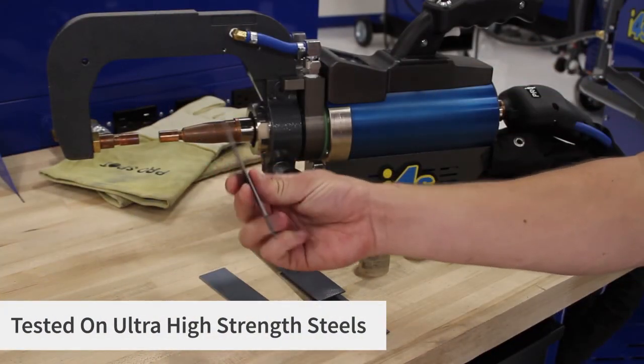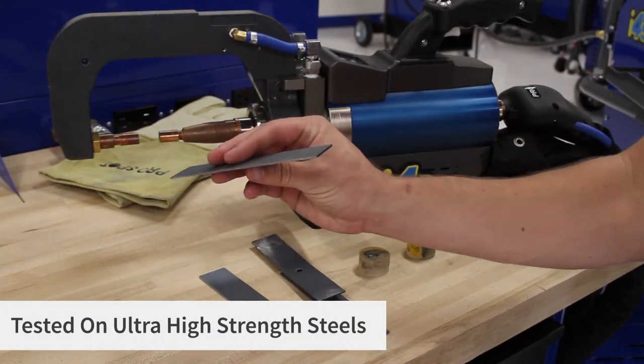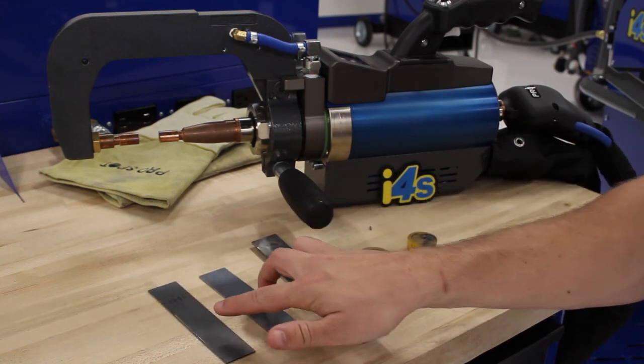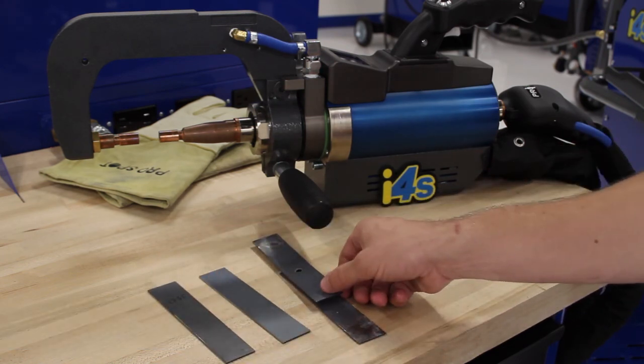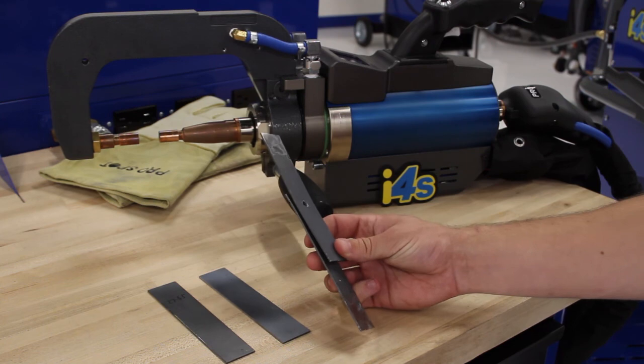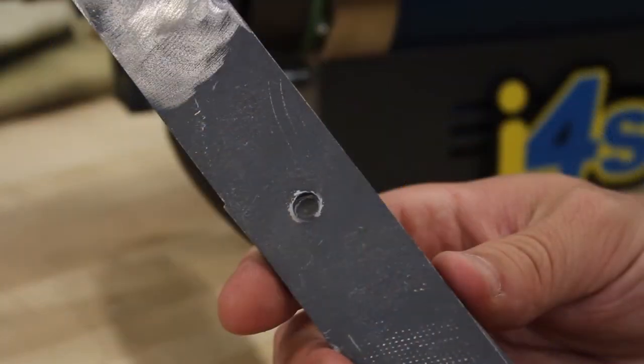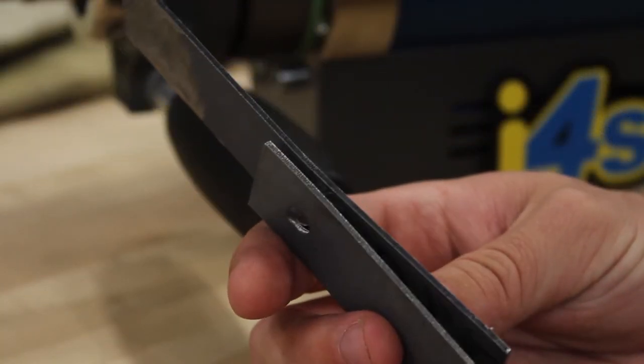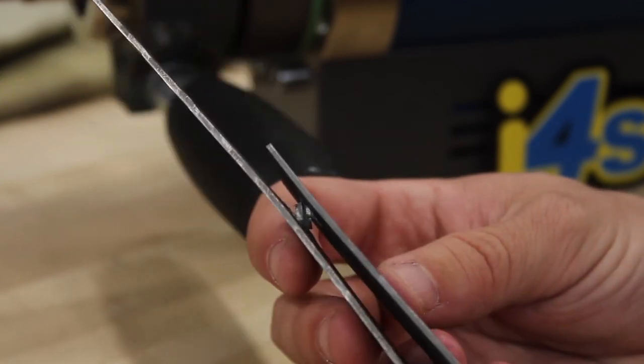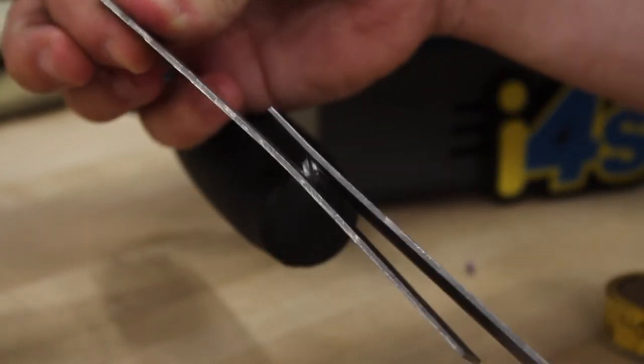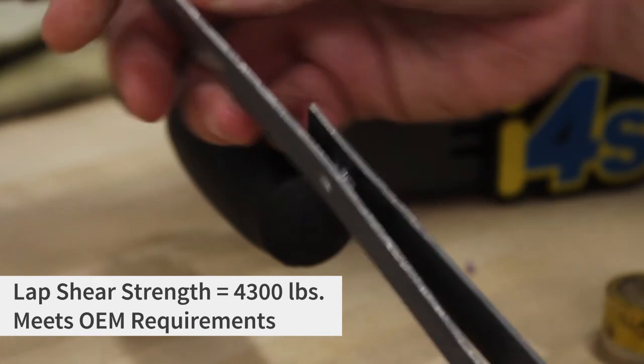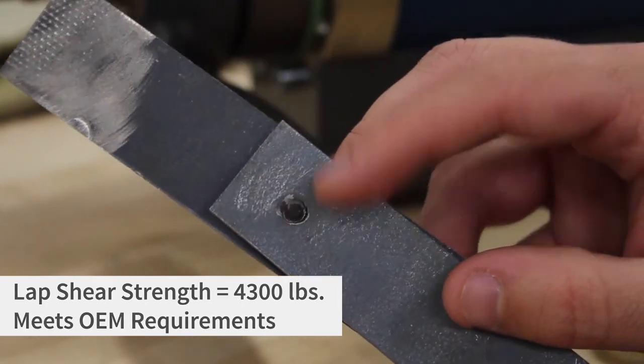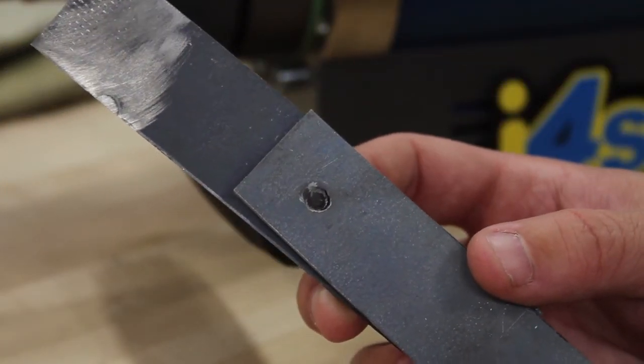So this is some of the high strength steel that we use for testing and evaluation. So first we start out with these two coupons, and then we actually spot weld them together and we find the pull strengths. So once we get a good recipe for the weld, we actually do a pull test on it. So we're actually tugging at both ends of it until the weld breaks. And so you can see right here, the weld's broken. It actually broke at over 4,000 pounds.